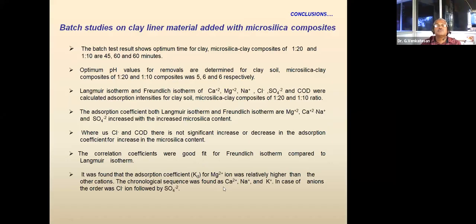Next, batch studies of clay liner material with the microsilica composites. It shows that the time optimization is 45 minutes for clay, and 60 and 60 minutes for the 1:20 and 1:10 ratios. Similarly, the pH obtained is 5, 6 and 6 for the ratios. For the Langmuir isotherm, the adsorption coefficient is also calculated here. Chloride and COD did not show a significant decrease in adsorption coefficient. The correlation coefficients were a good fit for the Freundlich isotherm compared with the Langmuir isotherm. The adsorption coefficient for magnesium was relatively higher than the other cations.